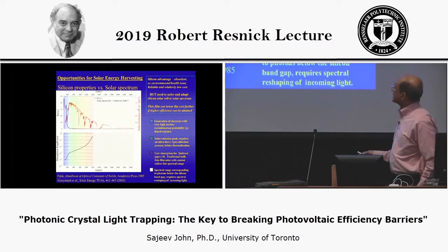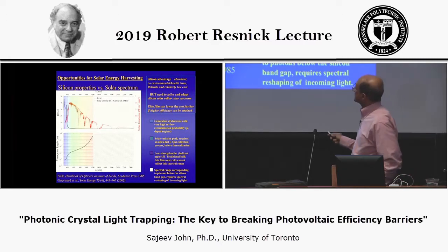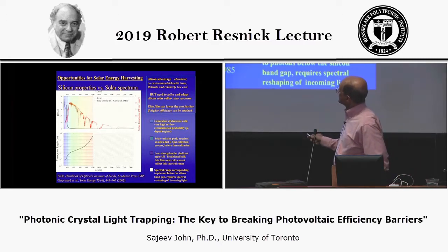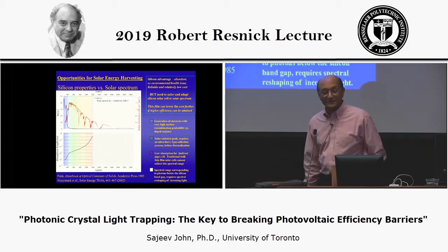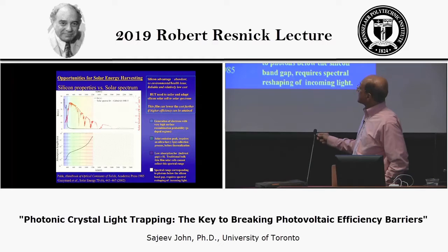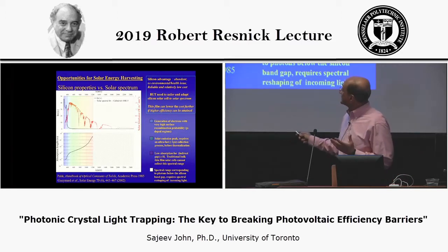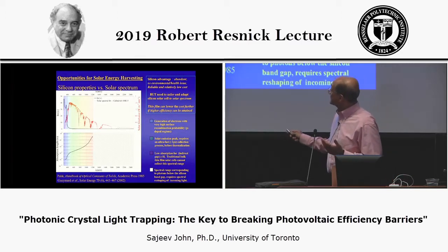Here you see a little bit more detail about the solar spectrum as it's seen on the face of the Earth. This is the red curve as a function of wavelength. It covers a very broad spectrum. And on that same graph, I've plotted the absorption capability of silicon as expressed by the imaginary part of the dielectric constant. That's this black curve. As you can see, the absorption is very good at short wavelengths, 500 nanometers and shorter.